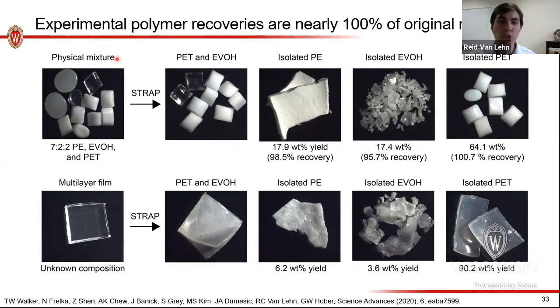At the top, I've just shown you a physical mixture where I'm essentially just mixing my different polymer components together so I can measure 100% recovery of each of these different components by doing the strap process. This is the actual multi-layer film provided to us by Amcor. For IP reasons, I can't tell you the exact composition of the film, but if I look at the yields of each of my different components, I would find that they're nearly 100% of what Amcor tells us is in it. So this addresses the question of how do we choose solvents and does experimental recovery work?